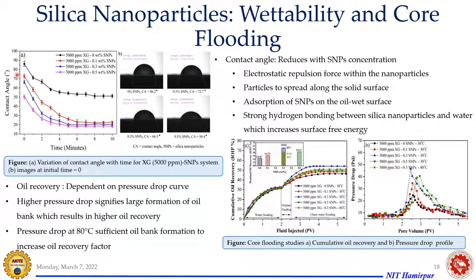So you can see this reduction at the very beginning gives you a clear idea of how effective these nanoparticles are in changing the wettability. And you can see that when the nanoparticle concentration is pretty high, the rate at which it changes the wettability from intermediate wet towards favorable water wet depends on the concentration of the nanoparticle.